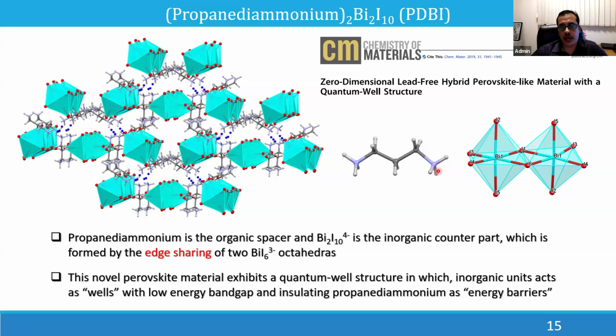So we made a new structure with this, and here you can see along one direction, along the c-axis, it is electronically connected. There is no hindrance from the organic component. But along the a-axis and b-axis, this is the x-axis and this is the y-axis, there is a barrier made with the organic part, and along the z-axis, it is not forming a barrier. So electronically, it is active along the c-axis in the crystallographic axis. I'm talking about the crystallographic axis. A and B, there is hindrance, and C, there is no hindrance.